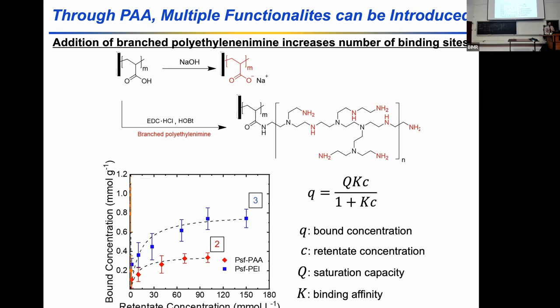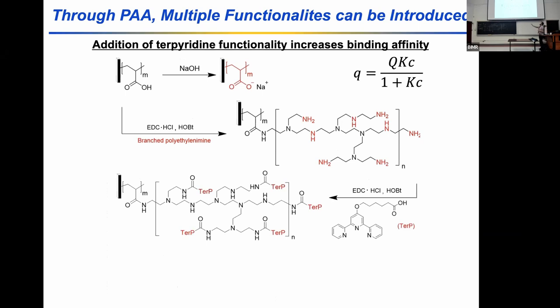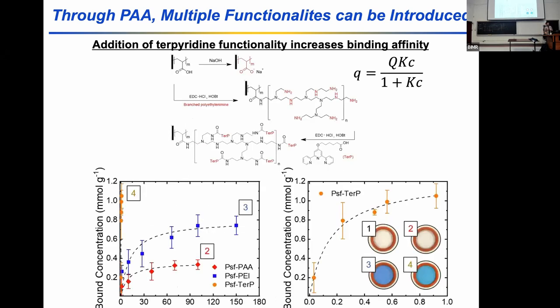And then we can go through one additional step and add a terpyridine functional group, being used by our collaborators in the Weber group, that has a known high affinity for transition metal ions. It's carboxylated, and so it can also be coupled to the PEI moieties. And the exciting thing is that we see this manifest in the Langmuir isotherm.